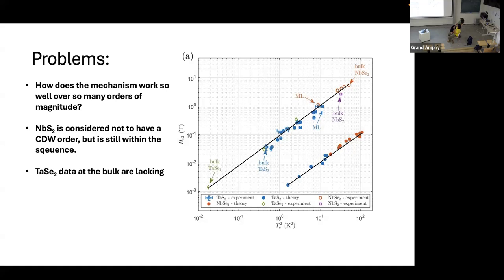If you go from thick to thin and thin to thick, it just doesn't make sense that the electron-phonon coupling would change so strongly. A second thing that can change is the structure of the Fermi surface, the population of electrons or holes. And it's actually pretty well known that bulk tantalum sulfide and tantalum selenide have roughly similar Fermi surfaces. They're not identical; one of the talks before showed they're slightly different, but not so different. And the Tcs are very, very different: 0.8 versus 7.2.